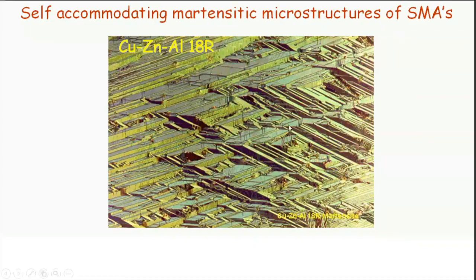It turns out that the free energy available for the nucleation is not very high. And you can just imagine, it's very close to room temperature also. We have already seen a transformation which is 80 degrees. These are all very low temperature, and the driving force is not high. And if you have a stress around the plate, that will act against that. That will dissuade the formation of the martensite. And the way it gets around this is by forming a self-accommodating plate group. So essentially, the parent phase around it does not see much because all of this cancels each other. So this self-accommodating martensitic microstructure is characteristic of the shape memory alloy.